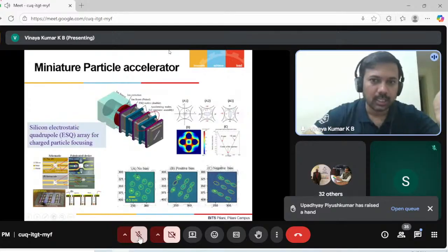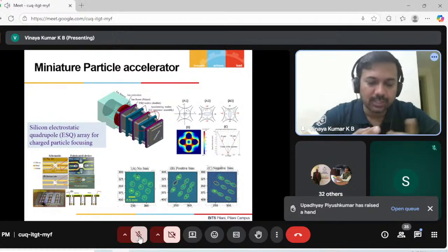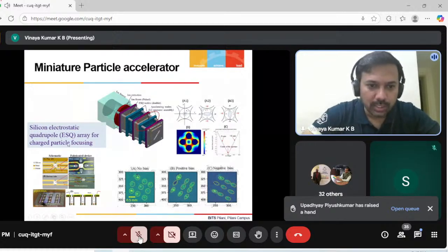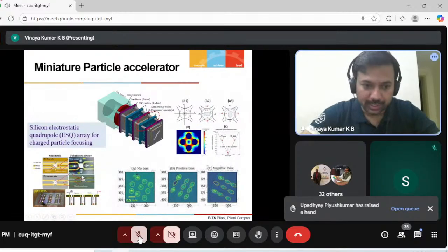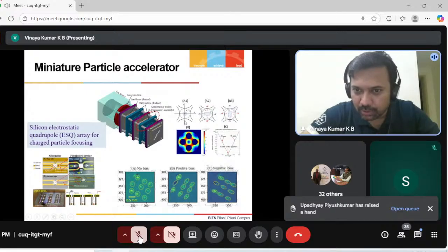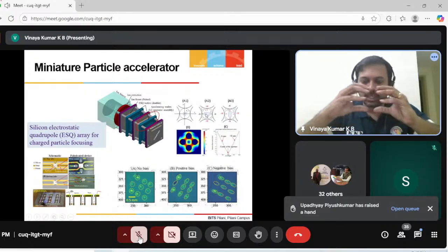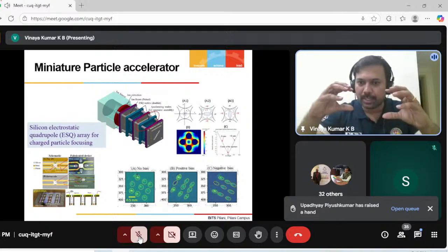And then when I was at Cornell University, we were working on a miniature particle accelerator for several applications. My contribution was building the electrostatic quadrupole. This is a complete silicon device. As you can see, there is a hole and there are 4 electrodes. You can apply positive, negative, positive, negative. You're able to generate an electric field which is 0 in the middle, and the electric field increases in both directions. If you apply only positive, positive and negative, negative, and the center beam is a charged argon beam, you're going to shape the beam in this fashion.